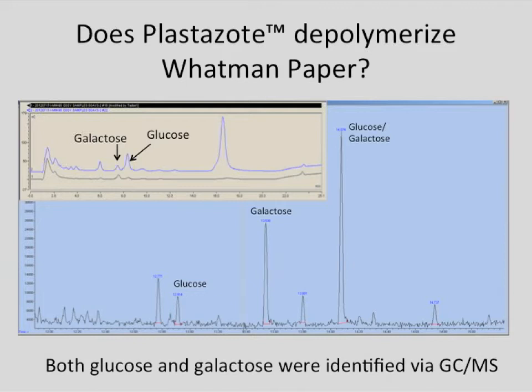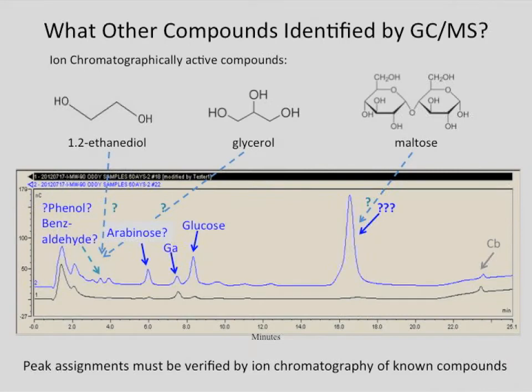Looking at all those results together, the two methods we used, one of the things we found with the trimethylsilylation was a trace amount of maltose. Maltose might actually show up much later - it's got a lot of hydroxides and looks a lot like cellobiose, just with a slightly different linkage between two sugar molecules. So this could be maltose, but if you look at the size of that peak and the fact that we only saw a trace amount in the GCMS, it would surprise me.